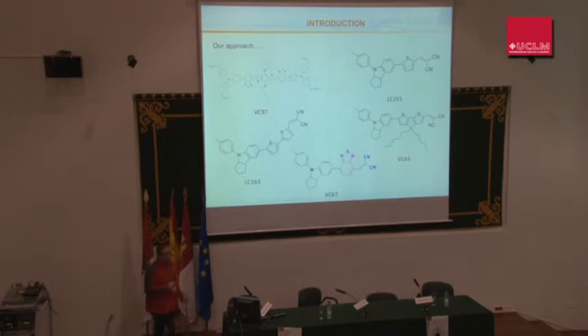And what happens is that when you excite these molecules in the UV-visible, you have a strong absorption in the visible because you have a charge transfer band from the charge going from the secondary electron donor to the pi bridge. So the HOMO and the LUMO of these molecules are delocalized. The LUMO is mainly in the cyano, and the HOMO is mainly in the indole, or in the case of the others, in the triphenylamine.